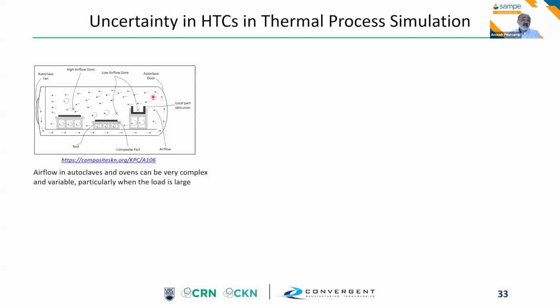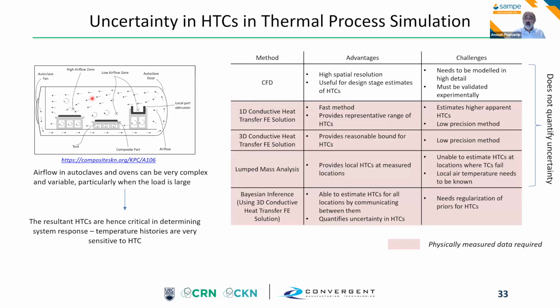Another one, which I think is really important, is uncertainty in your heat transfer coefficients in thermal process simulation, which is otherwise a very stable technology. And here, what's happening is you get very complex airflow in an oven or an autoclave. If the load is large, or you have a mixed load, you really need to understand what your HTCs are, because with airflow, the heat transfer coefficient actually plays a big role in thermal lags and actually thermal leads. So a lot of work has gone into trying to measure that.